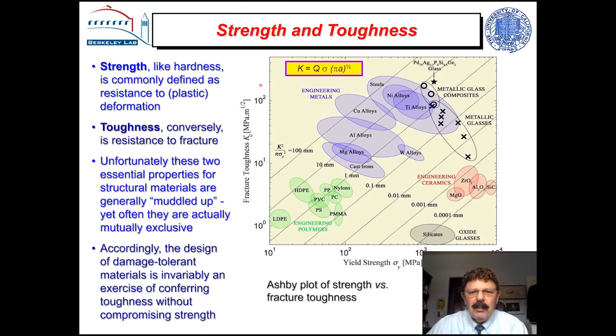If you look at this Ashby plot of the fracture toughness as a function of yield stress, you can see that for each class of materials, metals, polymers, and ceramics, there's often an inverse relationship between toughness and strength. And so when we generate a structural material, we really have to get both those properties. So that's often an exercise in compromise.